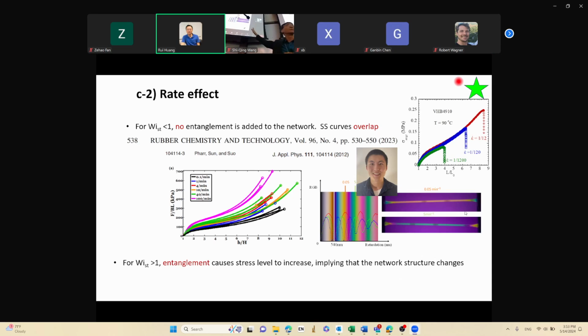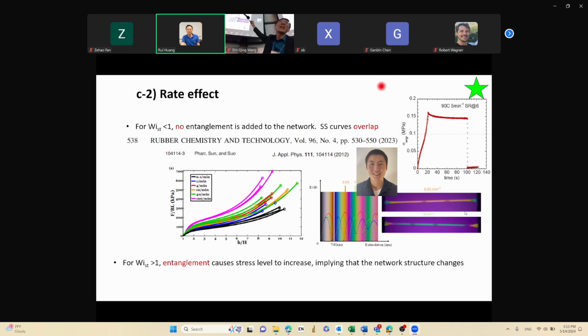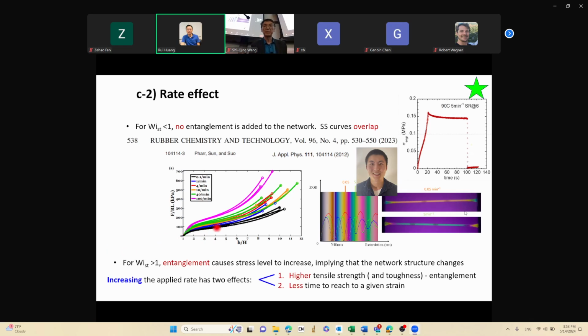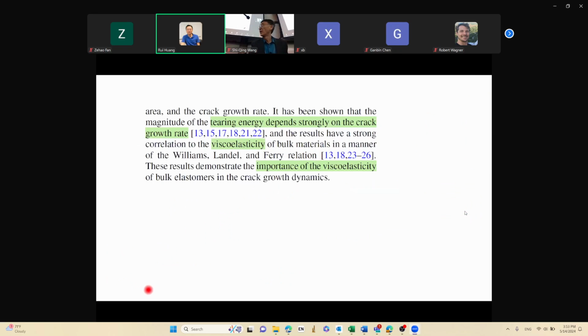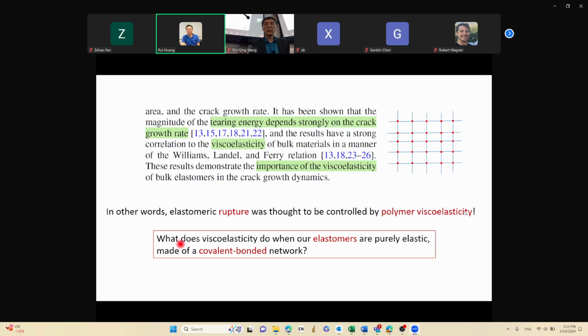So this is an entanglement-free region, in a sense. It collapses. Why? I can even show you, you do stress relaxation, stress doesn't relax. Purely elastic. The problem is much simpler. Okay, so I'm almost reaching the punchline. In the literature, we thought this was a viscoelastic problem, but it's not clear how that comes in to explain our pure elastic deformation problem here. It's purely elastic deformation.